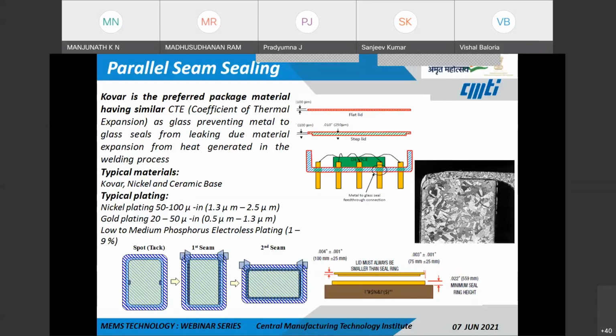Here, the lip of the lid, which is shown here, must be thin enough. Typically 100 to 150 microns will be the thickness of this lid, which allows the seal interface to reach the welding temperature very quickly, whereas the other portion of the lid will be at a lower temperature. The center of this lid can also be a thicker portion, which gives mechanical stability to the package.